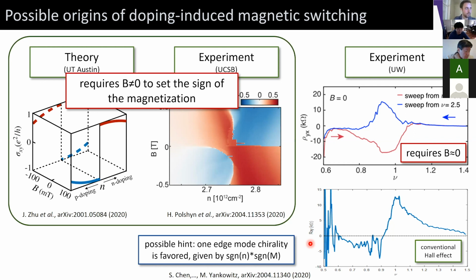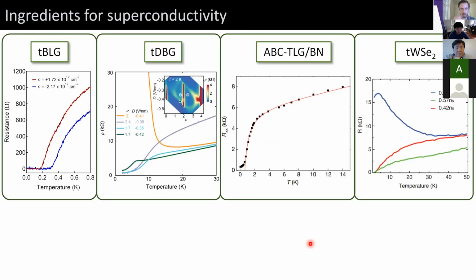Okay, so I have very little time left, so let me just say a few things very briefly. One question from all this is, what are the ingredients that are actually necessary for superconductivity? It seems to be robust in twisted bilayer graphene, but we think that in twisted double bilayer graphene, a similar effect is actually not indicative of superconductivity, but of spontaneous symmetry breaking. And there are other systems like ABC trilayer graphene and twisted WSe2 that exhibit similar phenomenology, but I think are more consistent with twisted double bilayer graphene than twisted bilayer graphene. So there are open questions still about which of these systems are actually superconducting and how carefully you have to interpret transport measurements as a function of temperature for identifying a superconductor.